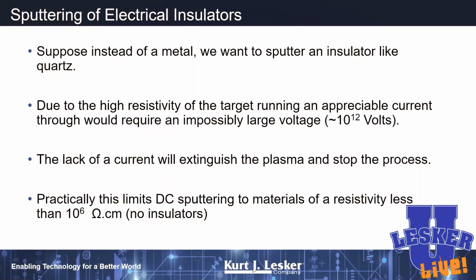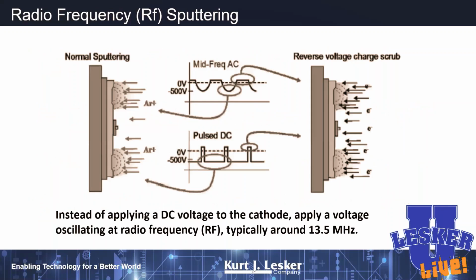So if I've got a true insulator, something with a resistivity more than 10 million ohm centimeters, I've got to graduate to a thing called radio frequency sputtering. And so in radio frequency sputtering, we're sort of doing the same thing that we did with pulse DC, where we've got positive argon ions here, and then we bombard them with electrons here. But with radio frequency sputtering, instead of having this nice crisp negative pulse, now we're going to vary that negative pulse a little bit in terms of its magnitude. And so it enables us to actually cleanse away any positive argon ions that get embedded in the target. But now we only have about half of the performance that we had with pulse DC. So now we're able to sputter insulators, but the deposition rate now is sort of like half of what we would have seen from a metal.